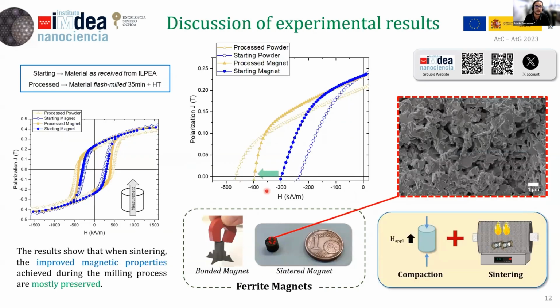And here you can see that we are using the starting powder, the material as we have received from our partner collaborator, and the processed powder made by us just by flash milling 35 minutes and a recrystallization process afterwards. So this magnet fabrication method is just the green compaction under the effect of magnetic field, and a sintering process at really high temperatures and long times to regain the mechanical properties of the magnet.